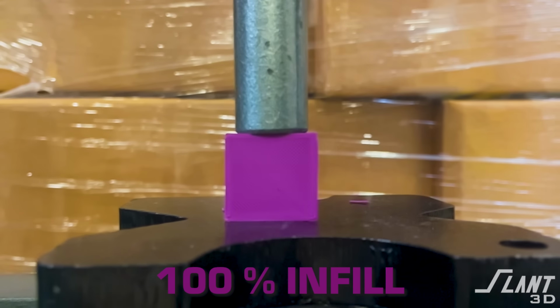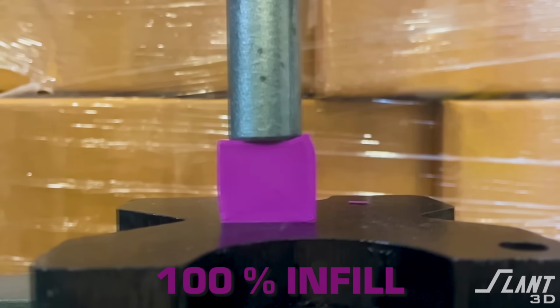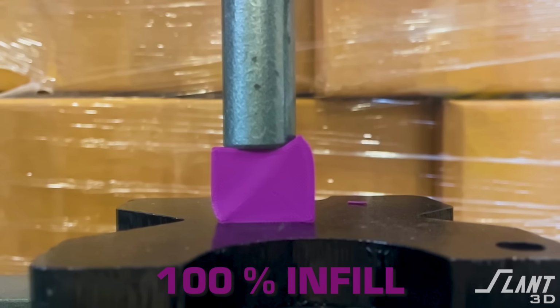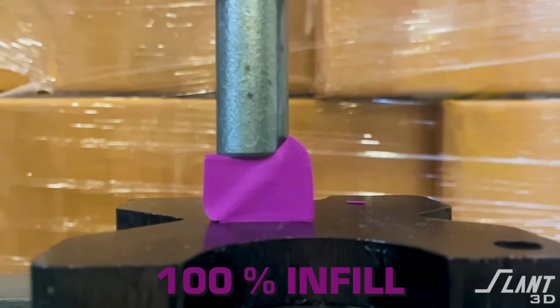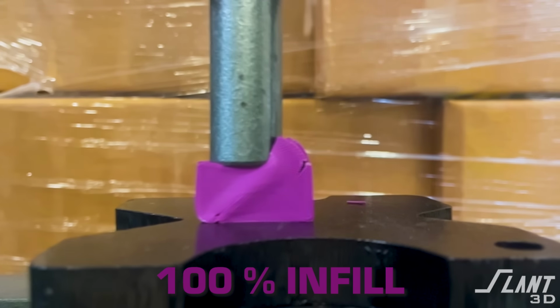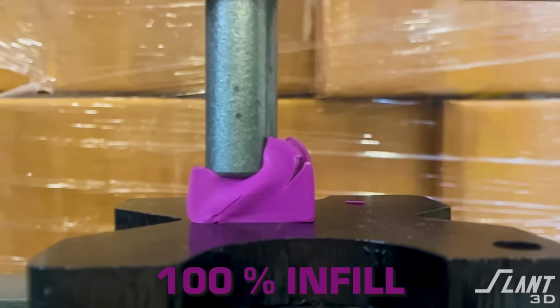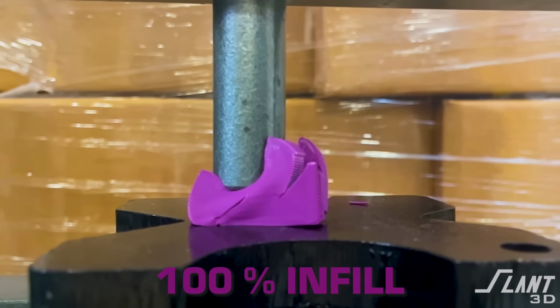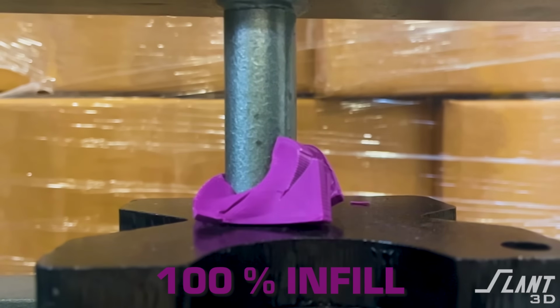Now going up to 100%. 100% fully solid has a lot different dynamics since every layer is able to interact with each other. It's almost isotropic to where it does not fail along the diagonals. It basically just crushes like any standard plastic part. So that was actually pretty darn insightful.